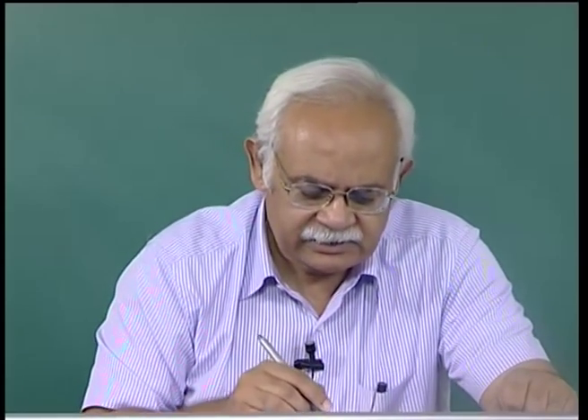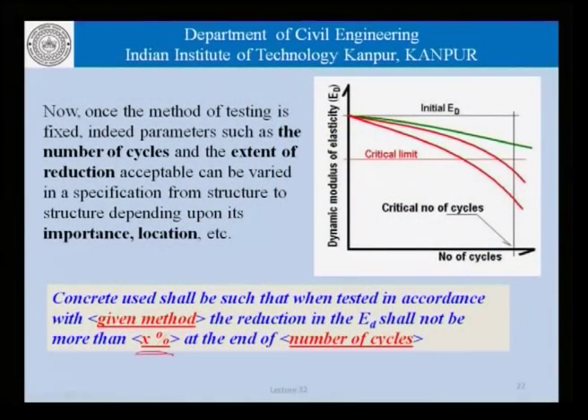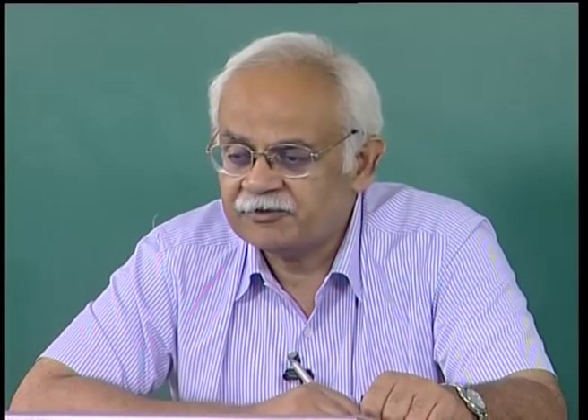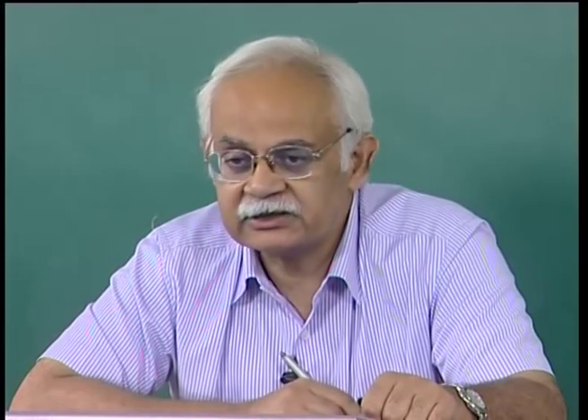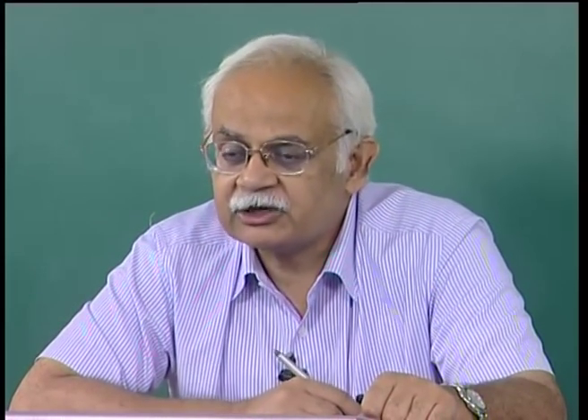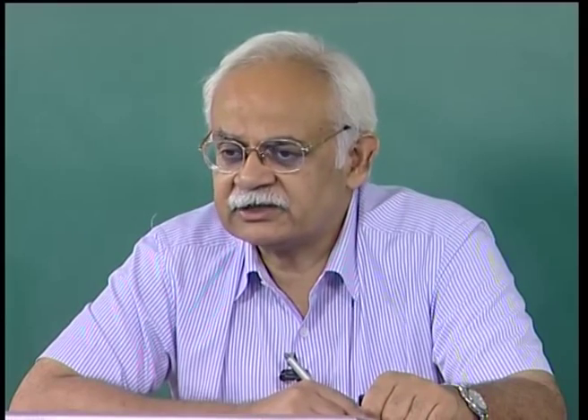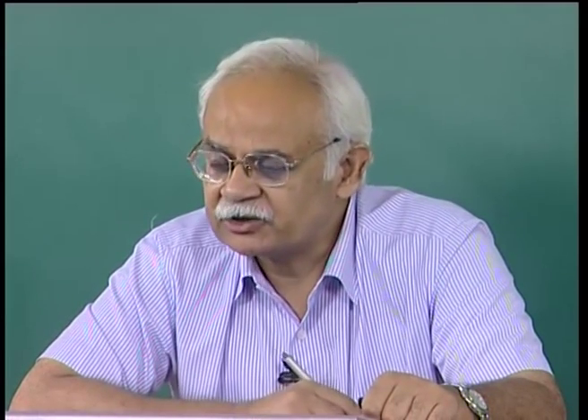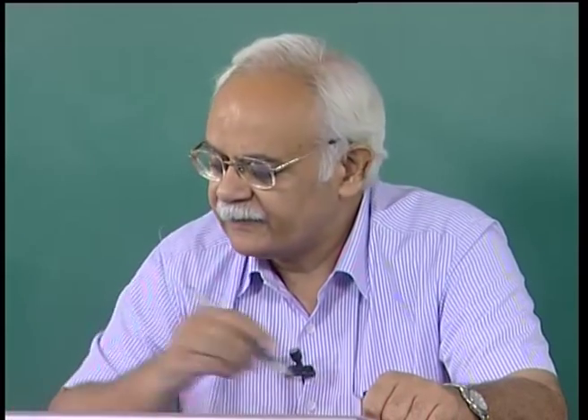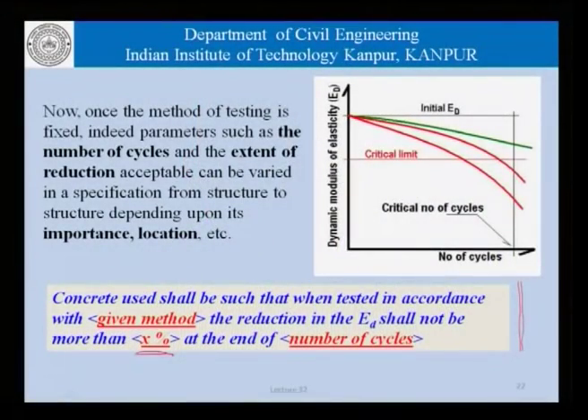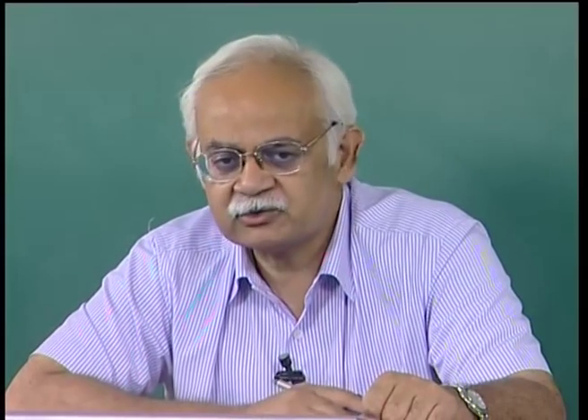And therefore, in certain cases we may accept, let us say, 20% reduction in E d in 100 cycles, but in certain cases we may just accept 10%. In certain cases maybe we will accept up to 30%. So, depending on what kind of a structural design we do, and what is the importance of the structure that we are trying to design, this is the kind of performance requirement that we can lay down when specifying a concrete. So, we carry out the design of the structure in the usual manner and then see that the concrete that we are going to use also meets this